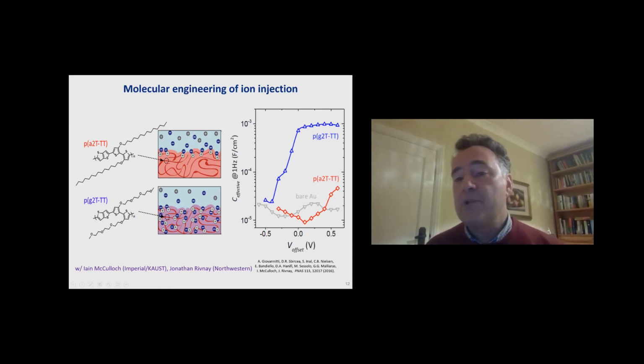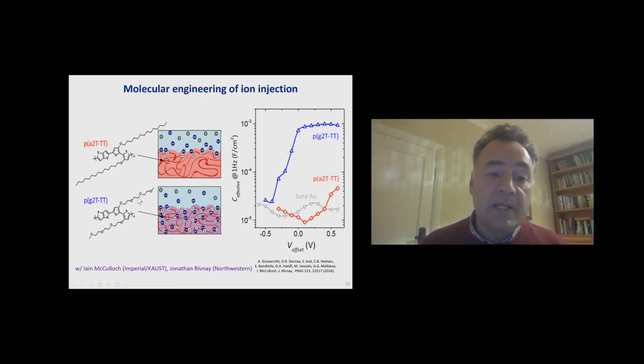So if you were to measure the so-called capacitance, which describes the strength of the interaction, it would be the same as that of a flat metal film. So a two-dimensional interaction, which is weak. On the other hand, in this material, the addition of oxygen atoms on the side chain allows ions to penetrate into the volume. And then all of a sudden, the capacitance increases quite a lot. So the strength of communication increases.